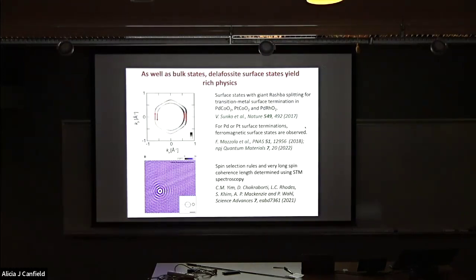And the Rashba deductions made from the photo emission tell you there would be some rather special spin selection rules when you do quasi-particle interference in STM. And Peter Wahl's group at St Andrews have indeed seen that those selection rules are obeyed and deduced a very long spin coherence length, which you might expect.